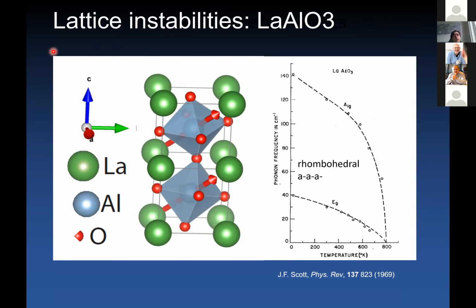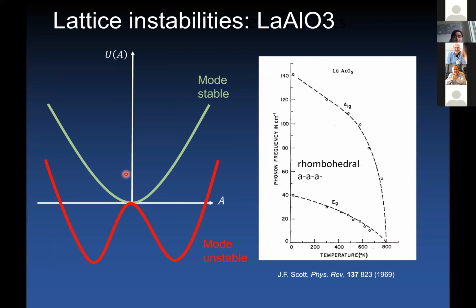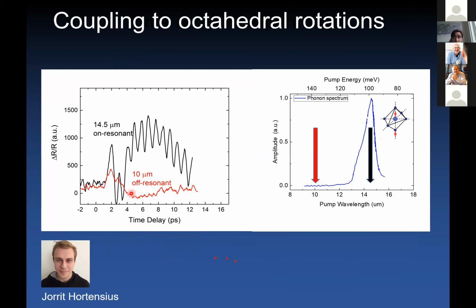And I want to show you that this is indeed the case with a simple case of lanthanum aluminate. So as I showed you before, lanthanum aluminate has a rhombohedral distortion at 800 Kelvin with a condensation of 2 modes. So even at room temperature, it is a crystal that has some anharmonic behavior. So we have a mode that goes from being stable to being unstable as a function of temperature, and this is associated with lattice anharmonicities.